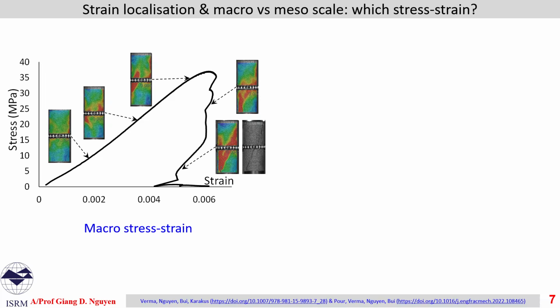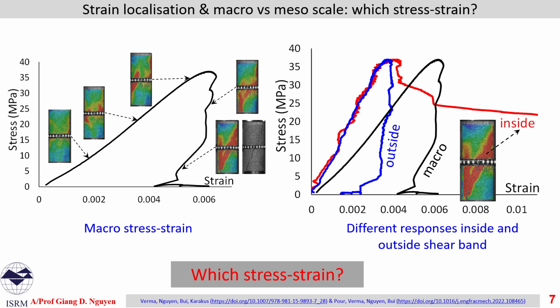So the question here is, which stress-strain relationship will we use? We know the strain will be different, so we plot the average one here. They will also be different across the three specimens. And if we take a further step, using digital image correlation to work out the stress-strain relationship, stress is assumed roughly the same because it needs to meet the equilibrium condition across the shear band. Strain, as we know, is very different.